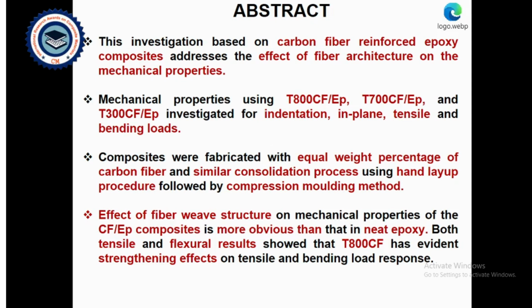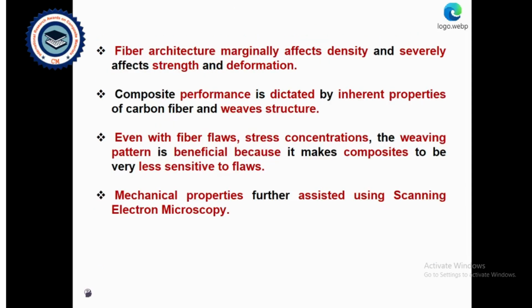Both the tensile and flexural results showed that T800 carbon fiber epoxy composites have evident strengthening effects on the tensile and bending load response. Also, fiber architecture marginally affects density and severely affects strength and deformation. Here, the composite performance is dictated by inherent properties and fiber weave and structure. Even with fiber flaws, porosity, defects, and stress concentrations, the weaving pattern is so beneficial that it makes composites more or less insensitive to flaws. Finally, mechanical properties were further assessed using the SEM, that is, scanning electron microscope.